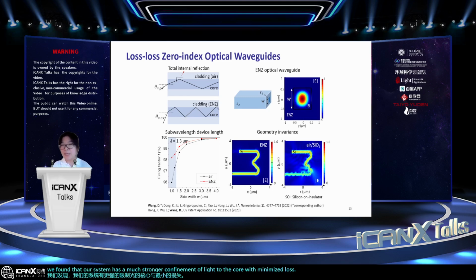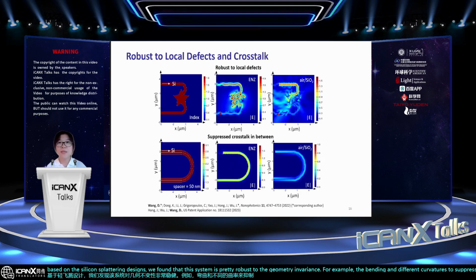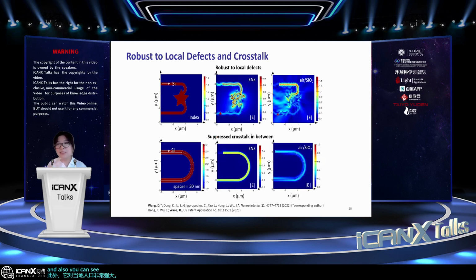And as we compare to the conventional waveguides based on silicon-on-insulator designs, we found that this system is pretty robust to geometry variation, for example, bending and different curvatures, to suppress the optical scattering loss. Also, it's robust to local geometry defects. And you can also see the suppressed crosstalk between waveguides when you have the ENZ as a cladding layer. In this case, this can serve as a promising future system for low loss integrated photonic circuits.